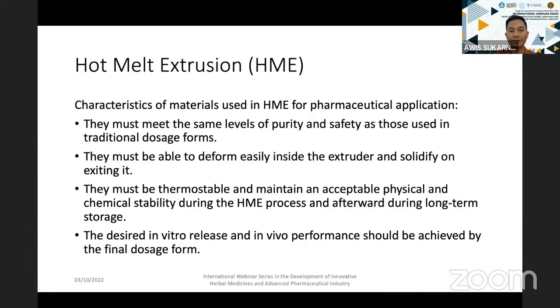And then the next one, it must be able to deform easily inside the extruder and solidify on exiting it. So in this one, like I said before, the polymer or the carrier that you're going to use needs to have a glass transition temperature. So it means it's going to soften. The right word is actually soften. It's not melt. It will soften the material, and then upon the exit, they can blow the cool gas, the cool air. So upon the exit, it starts to harden, so you can retain the shape. And then the other one is you need to look at the, what do you call it?